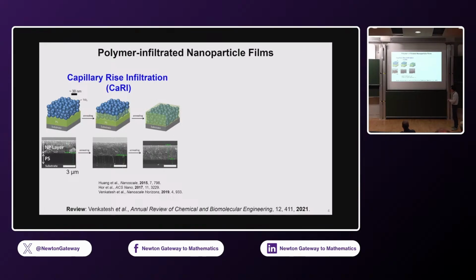Okay? And I'll show you more quantitatively later, but the thickness of this nanoparticle layer stays more or less constant, which means that the particle-particle distance does not change. The volume fraction of the particles does not change after the polymer has gone in. So the particle packing has approximately 64 volume% of nanoparticles. It's essentially random close packing of spheres. So at the end of the day, you have this composite that you generate very simply by just heating it, and you end up with 64 volume% of nanoparticles.